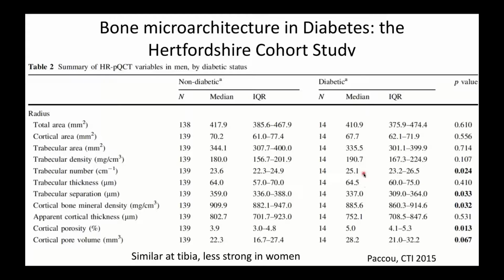If anything, trabecular separation is less, and cortical density here is now somewhat lower, pertaining to an increase in cortical porosity. Not a huge difference, 4%, 5%, but it's significant. So that points now to, again, no alteration in trabecular structures, but potentially a small difference with increased cortical porosity.